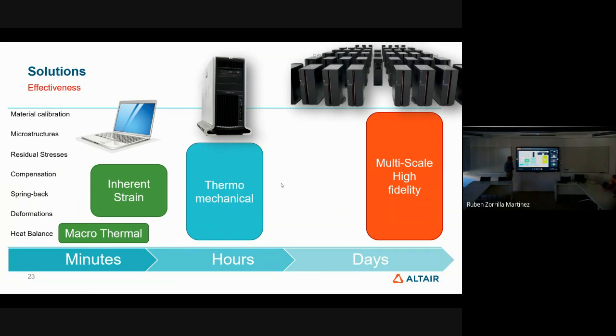So one of the main ideas here is to understand what you can do with this solver, because you cannot predict many things with it. For instance, with inherent strain, you cannot do material calibration. It doesn't even have temperature inside, so you cannot do, for example, microstructure, because you don't calculate correctly the temperature gradient, which is the most important thing to calculate microstructures. Residual stresses, in my opinion, are not accurate. Okay, they give you some idea of where it goes, for instance beyond the yield stress, which is the most important result people usually want.